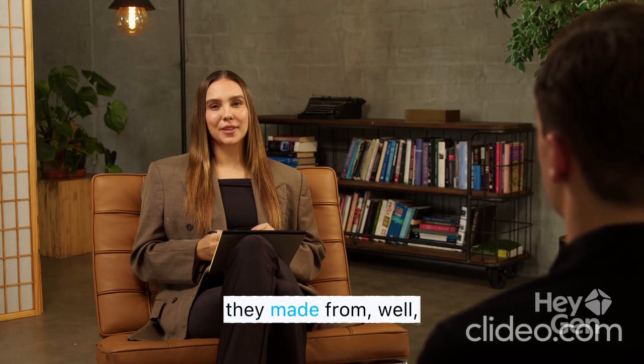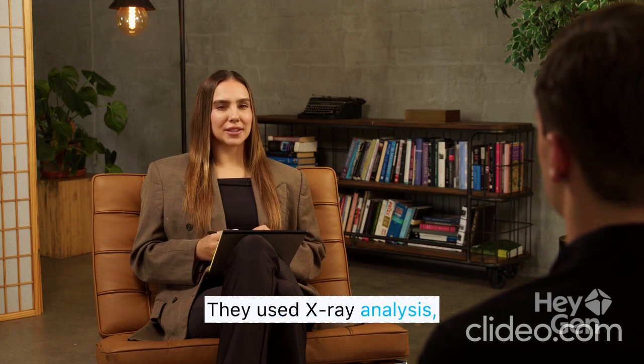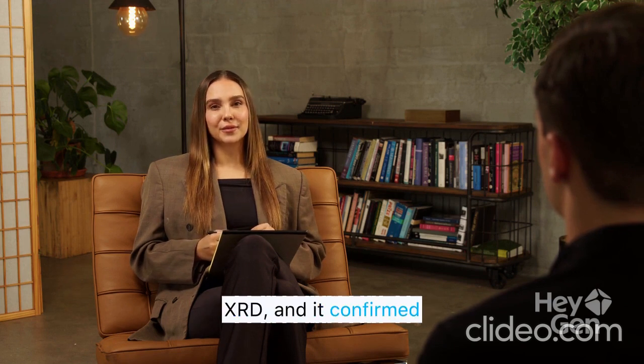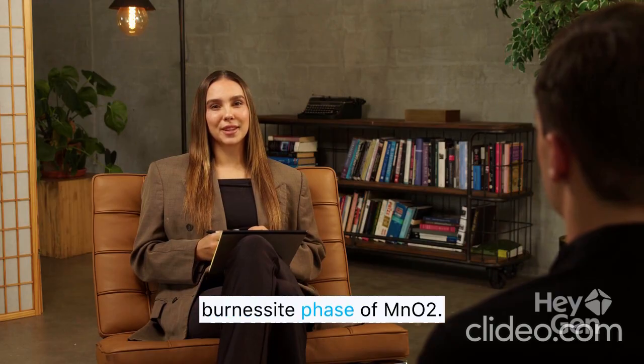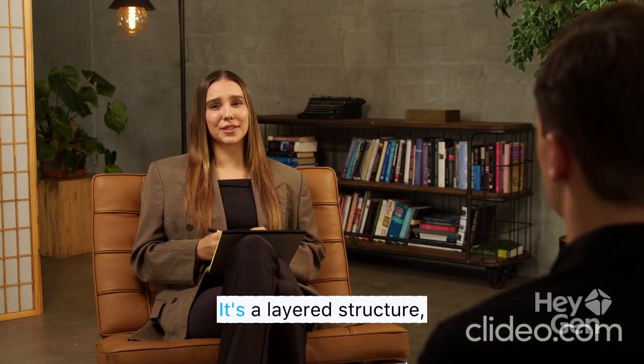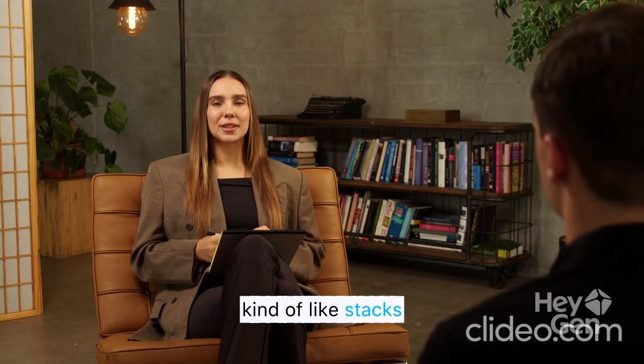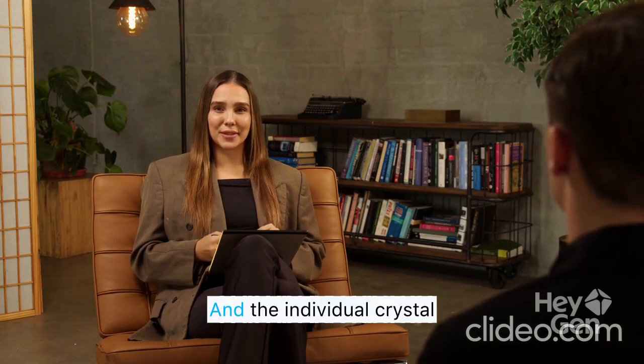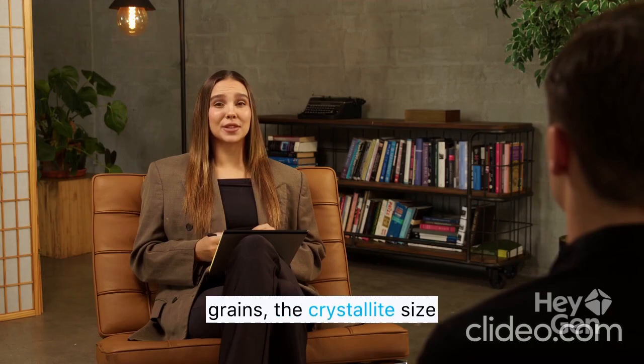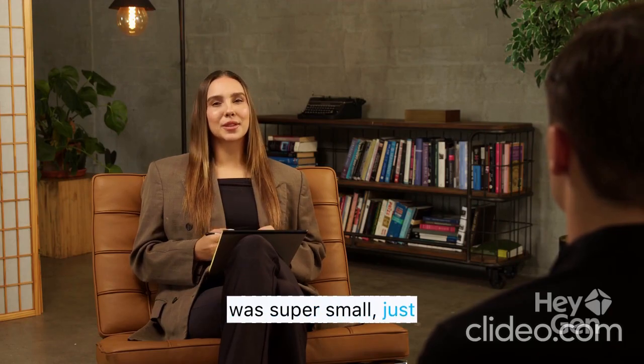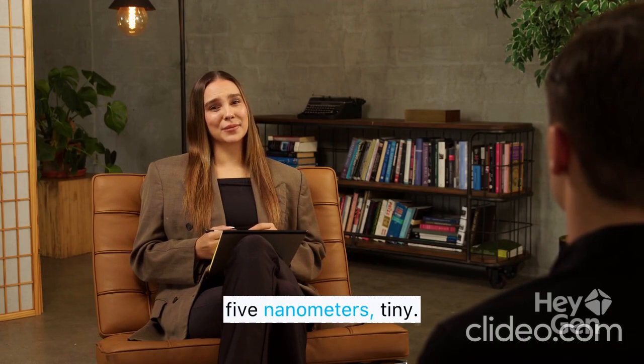What did the analysis show about this stuff they made from battery waste? The characterization was key. They used X-ray analysis, XRD, and it confirmed the material was the birnessite phase of MnO2. Birnessite, what's that like? It's a layered structure, kind of like stacks of incredibly thin microscopic sheets. And the crystallite size was super small, just 5 nanometers, tiny.